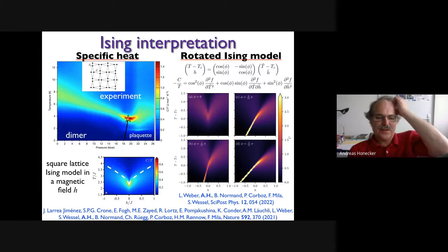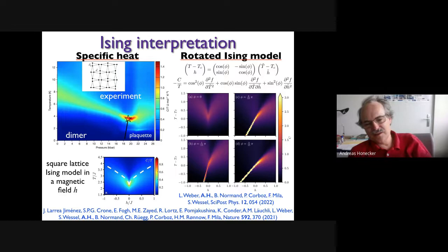And so after we published that work, we had a young guy, Lukas Weber, who came up with an idea to relate this to what is going on in water. Well, the Ising model looks a bit like strontium copper borate, but doesn't look like water. Now, what Lukas came up with is the idea to say, well, wait a minute, how should I know the temperature axis is temperature axis, and magnetic field corresponds to pressure? I might actually have a rotation of these parameters. And so if you change parameters of temperature and field, then you actually mix observables.